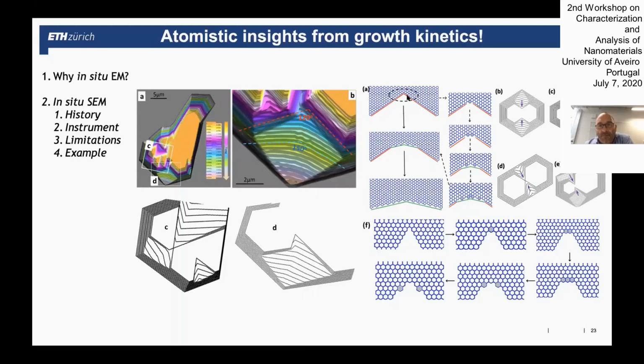And we actually understood that it is during the growth where you have the nucleation of a new row all the time, that the kink formation energy is minimal here in the concave corner. So it's easiest to attach a carbon atom right here in the corner if the two domains are co-oriented. So if it's really uniformly oriented graphene that merges, then you can easily attach a carbon in this place here. It's the easiest place to attach a carbon atom. And then once you have attached this carbon atom, you can fill these two positions with the next carbon atoms.